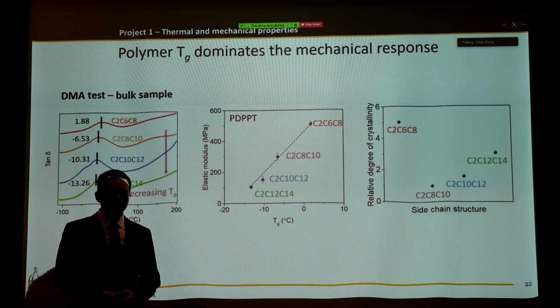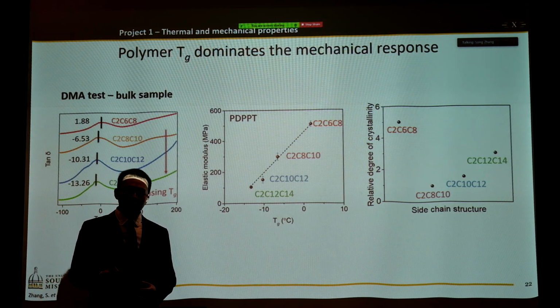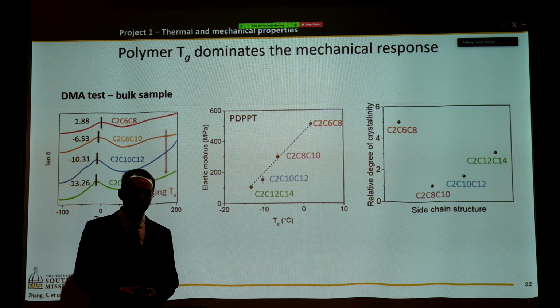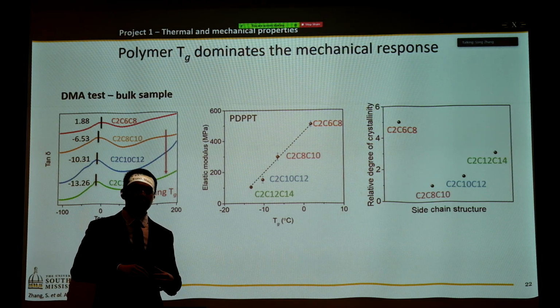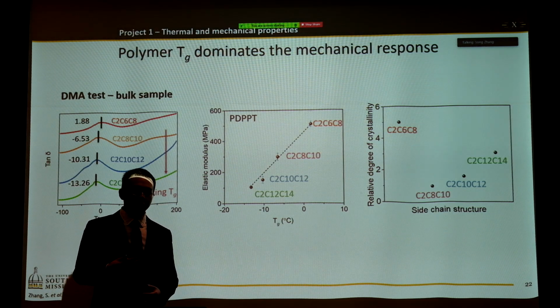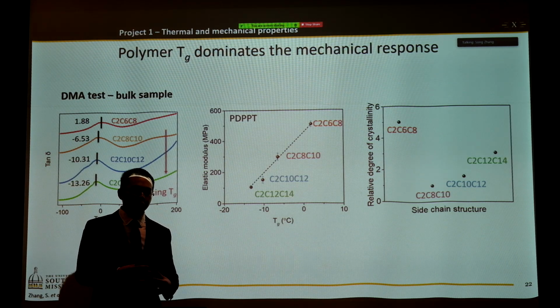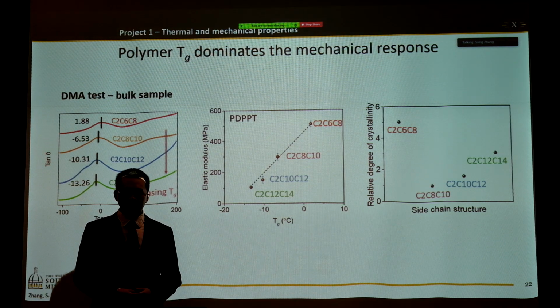Now let's take a look at the glass transition behavior on the DMA. We find that the Tg decreases with increasing side chain length, which is expected. And the elastic modulus shows a very linear relationship versus the glass transition, while the degree of crystallinity does not play a very important role in the determination of mechanical response.